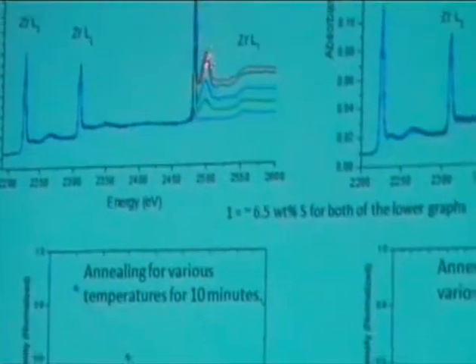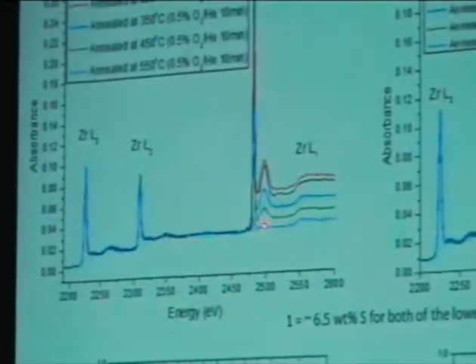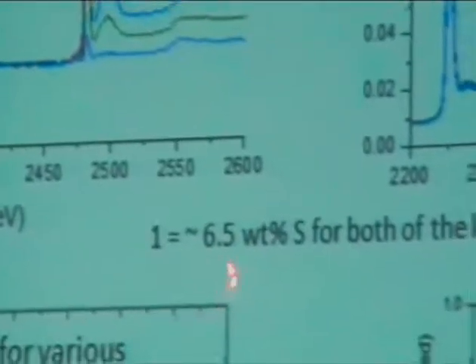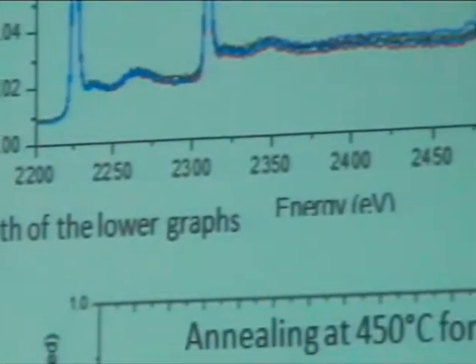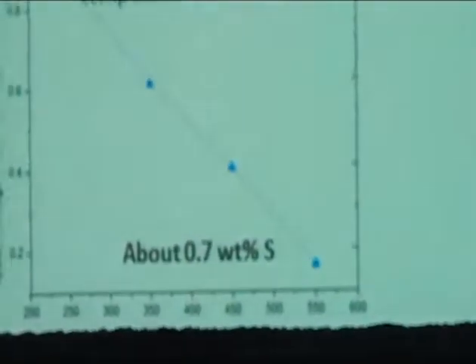So there we know that all the sulfate that is retained after this thermal treatment is interacting with zirconia. We can actually turn this into a very expensive chemical analysis, you know, a $50 or $100 million spectrometer, depending on how much sulfur you have. If you normalize this to the intensity of the zirconium L3, then looking at this relative intensity, we can determine the sulfur content. So when we started out at initial impregnation, we had 6.5 weight percent, and we'll just normalize to that. And then in this case, we are looking at the intensity of the sulfur as a function of thermal treatment, 250, 350, 450, 550.